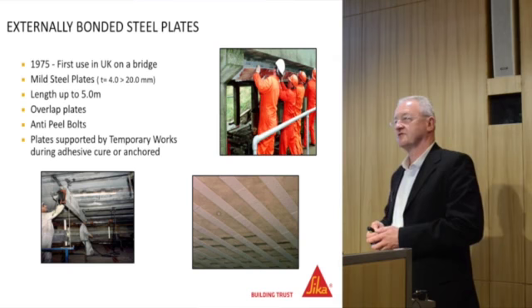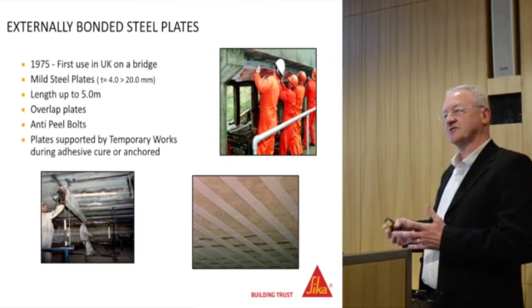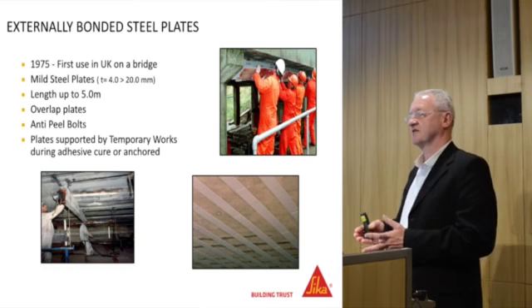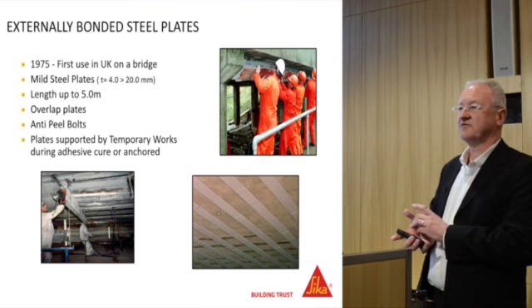1975 was the first use of the system on a bridge in the UK — Quinton Bridge. All the experience we have now shows that plates have always been around 4 to 20 millimetres in thickness, which does give certain problems when they are installed. Maximum length is around five metres, which could be manhandled by a team of four or five — so you can see there are practical restrictions there as well.